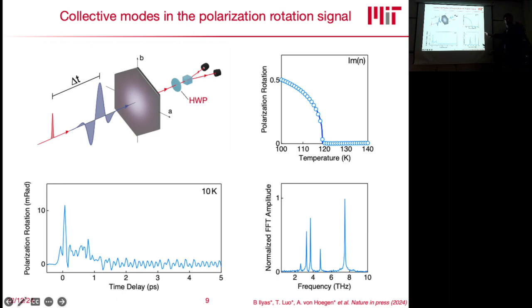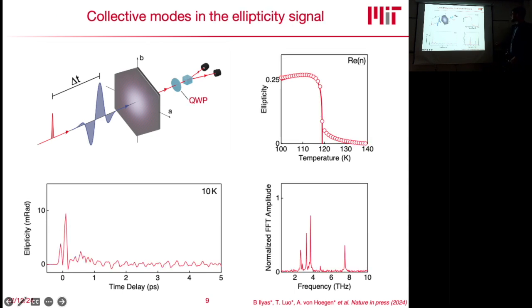And if you take a Fourier transform of this, you actually end up with this. You get these very, very sharp peaks that live on the order of hundreds of picoseconds. So they live for a very, very long time. This is why they are so narrow. And if we probe the same dynamics using the quarter wave plate, we get something very, very similar. So we see the same peaks here. We get very strong oscillations here. So both of these features are able to measure the transient features of this material.